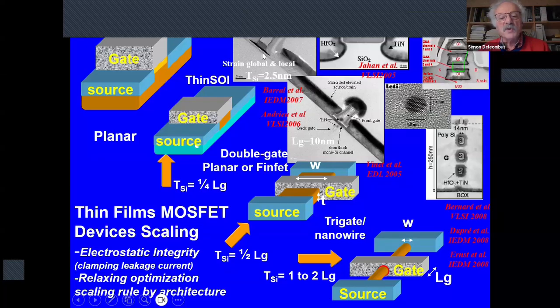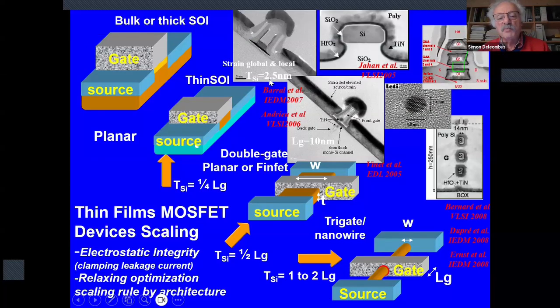You can see, for example, fully depleted SOI as thin as 2.5 nanometer. Here you have a tri-gate. Here you have a double gate with very aggressive gate length. Then nanobeams and nanowires that we have shown as early as 2006 and published in 2008. So well before Intel, just to mention it.